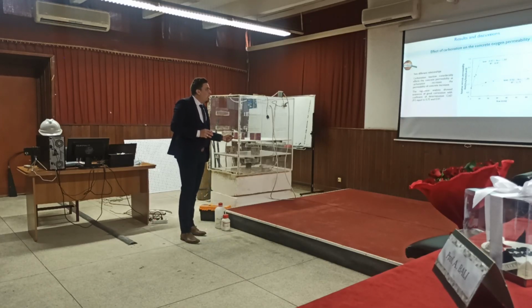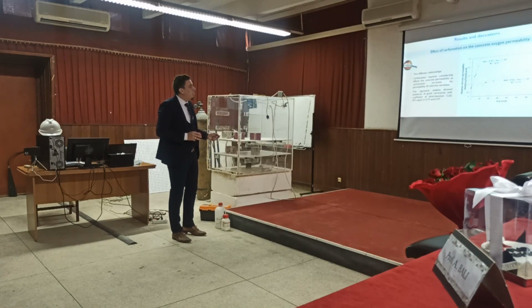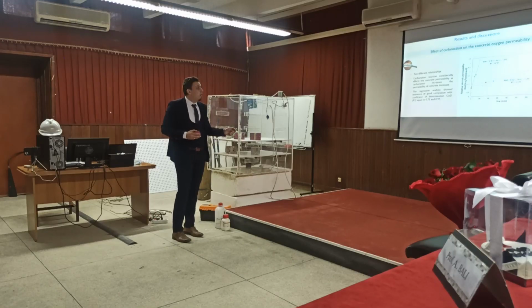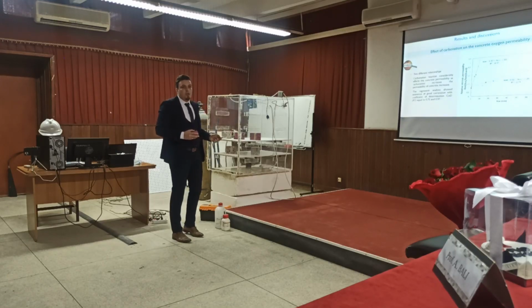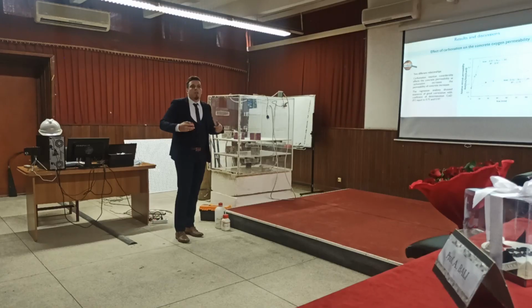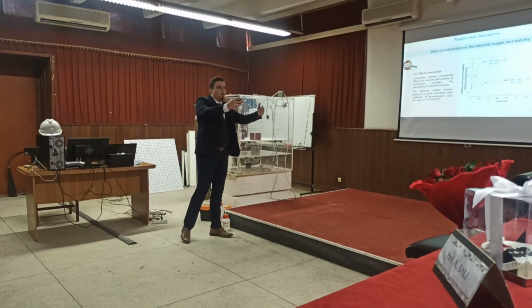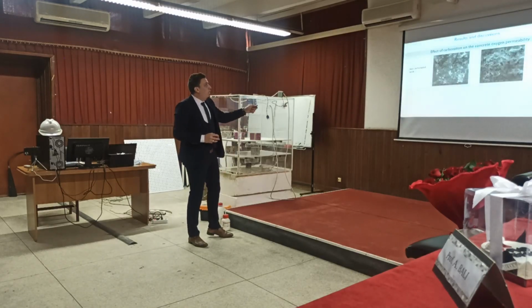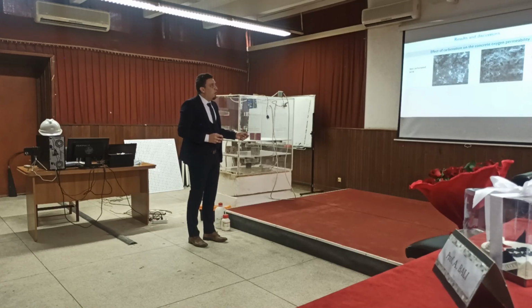What we found, not as expected, is that the carbonation reaction considerably affects the concrete permeability. As the carbonation increases, the permeability of concrete increases. And we also find that we have good correlations for both relationships. In order to justify these results, which is the increase of the permeability, we worked with images of the carbonated zone and the non-carbonated zone.